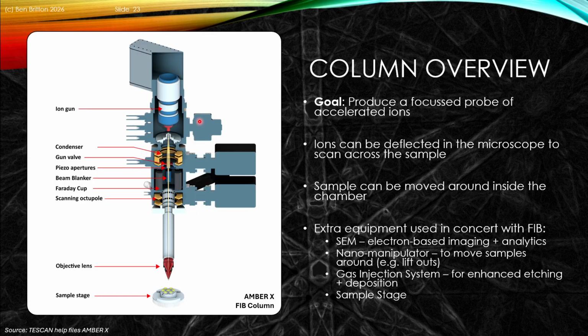So a focused ion beam instrument is established, and the key detail is how the FIB column is working. The FIB column looks in some ways quite similar to an electron microscope. So we basically have the source of the ions. We have the so-called ion gun that sits often at the top of the column. And then we have a series of effectively condenser lenses, gun valves, and a few other bits and pieces, as well as some apertures in the system that enable us to down select to a particular probe current.